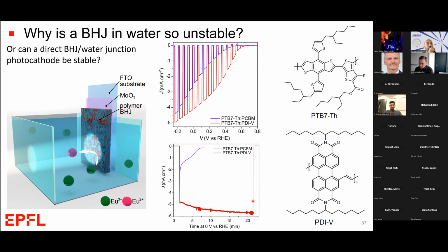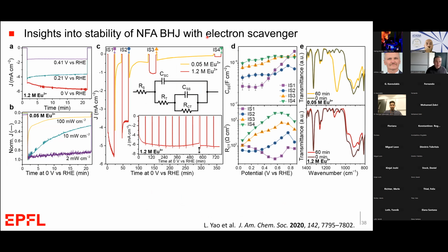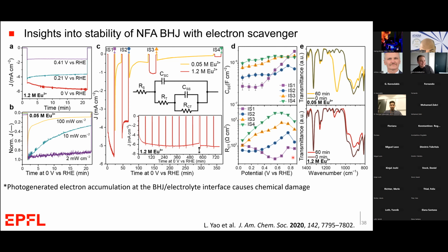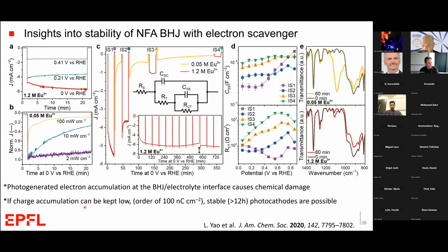reduction reaction. Now, I'm probably running out of time, so I don't have time to explain all of the detailed photoelectrochemical results that we have performed on these films. But the long story short is that we've identified the limitations of stability of these photocathodes due to an electron accumulation at the bulk heterojunction interface, which causes chemical damage, which we can see here by the FTIR before and after under certain conditions. And using electrochemical impedance spectroscopy, we can actually quantify the amount of charge accumulation.